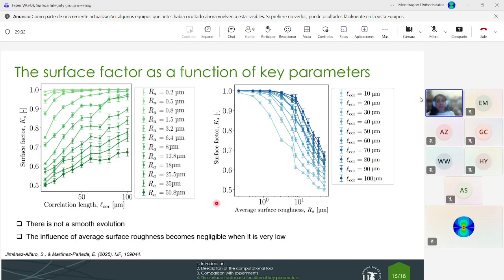We can also represent this data in a different way, as you can see here, where we express the surface factor as a function of the correlation length for different values of the average surface roughness, and the opposite case here. And it's very interesting because we can observe that there's not a smooth evolution in this tendency. This is because we are working with a stochastic phenomenon. So as you can see here, we have these bars representing the stochastics. So maybe the smooth evolution is at a point between these bars. That's why we have these strange peaks in the evolution. And another conclusion that we also observed in the operational map is that for low values of the average surface roughness, we can obtain a negligible effect even for low or big values of the correlation length. So the surface roughness plays almost no role in the surface factor.